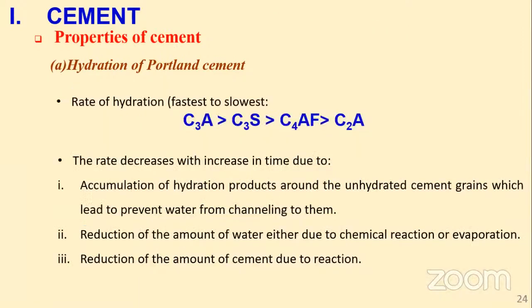So this is the rate of hydration from fastest to slowest. Tricalcium aluminate is the one that is very reactive, followed by tricalcium silicate. And that's why we need to slow down this using gypsum so that this one can start.